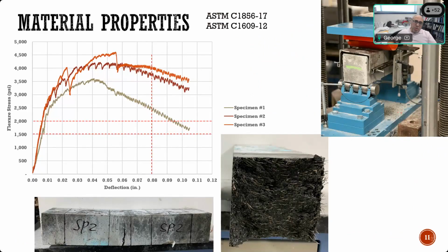Another test that is very important for UHPC is the flexural test, which is a 4-point bending or third-point loading, where you have a prism made of the UHPC and loaded at 2 points in the middle. This is a 12-inch span, a 14-inch prism, 3x3 or 4x4. There are two types of prisms, and you test it, not just looking for the maximum load that breaks it, but we're looking for the entire load deflection curve.